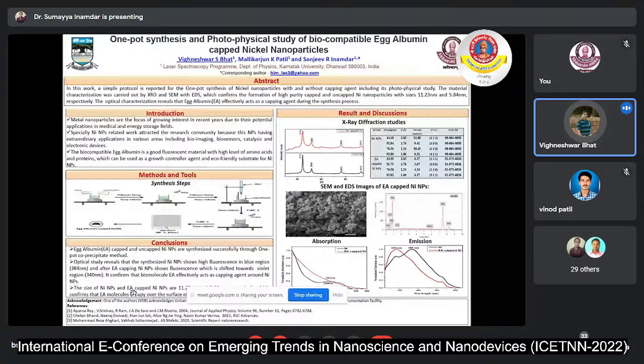Here, four major peaks are obtained at the planes of 111, 200, 220, and 311. Both show FCC nickel structure. And I have determined the interplanar spacing, FWHM, and size of the synthesized nanoparticles. And also the interesting fact is that no additional peaks are observed. That means without any impurity phases, we got pure FCC nickel nanoparticles.